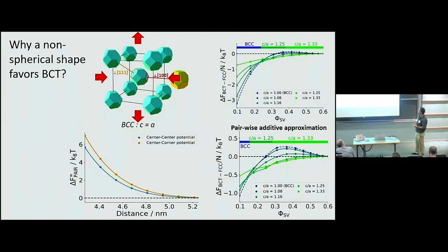The idea here is that there are two different types of interactions. The nanoparticles can interact through this hexagonal facet or through this square facet. And if you look at the pair potential between these two interactions, they are, of course, different. They would be exactly the same for spherical nanoparticles, but for these particles they are different. And now this center-to-corner potential is a little bit more repulsive than the center-to-center interaction potential, and we believe that this is what breaks the symmetry of the system and allows it to achieve a tetragonal distortion, right? Again, this is just a geometrical effect. You don't need any difference in the chemistry of the facet. It's just because of the geometry of the particles.